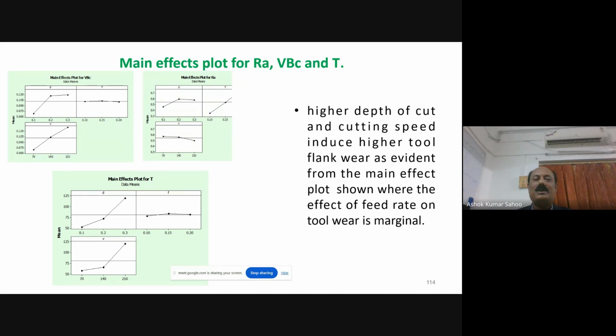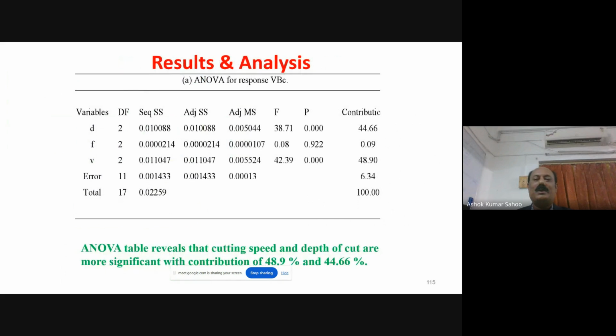Cutting speed is found to be the most significant parameter for tool wear. Feed is for the roughness, and the cutting speed is for the cutting temperature. As per the main effect plot and the ANOVA analysis, the depth of cut and the cutting speed are found to be the most significant parameters for tool wear progression, as the p value is less than 0.05 at 95% confidence level.